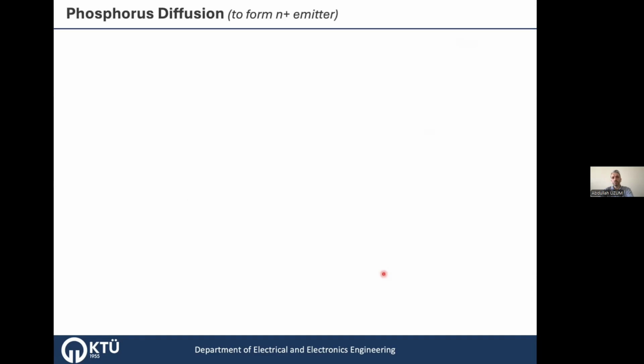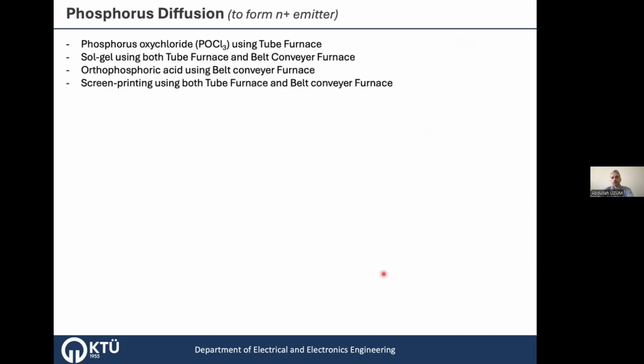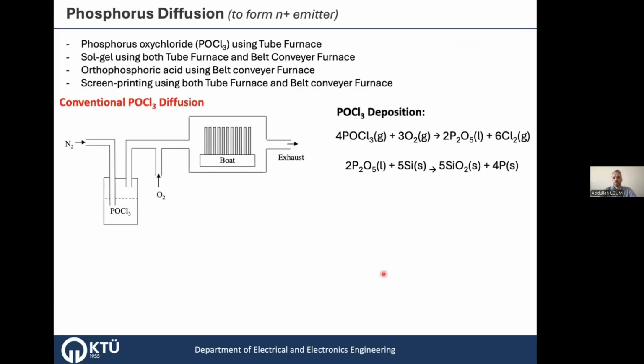After that, again, we have the N-type emitter formation. The standard technique for this is POCl3 diffusion, but it can also be done with sol-gel processes, spray, or screen printing processes. The POCl3 diffusion actually, POCl3 is a liquid, and it happens in 2 steps. In the first step, the POCl3 liquid is bubbled with N2 gas, and this evaporated POCl3 gas goes into the tube or tank like this, onto the surface of the silicon wafers. These are silicon wafers here. And this is the low temperature process. We call it pre-deposition.